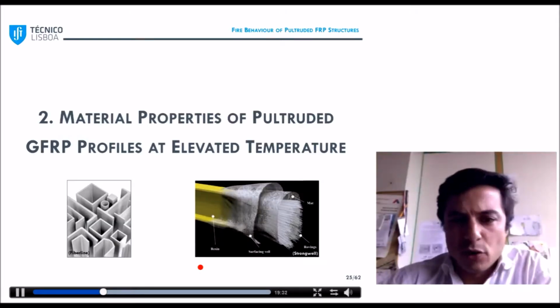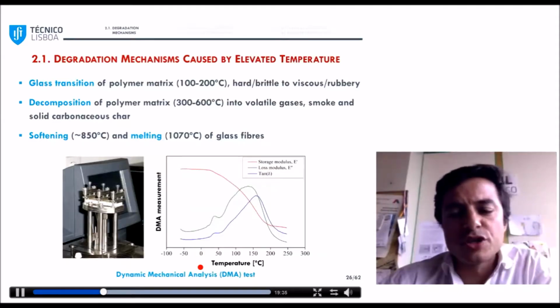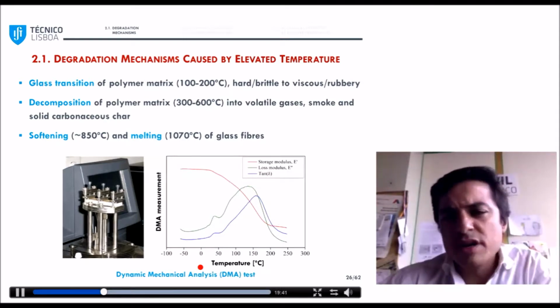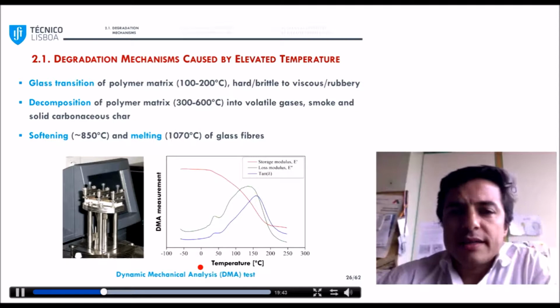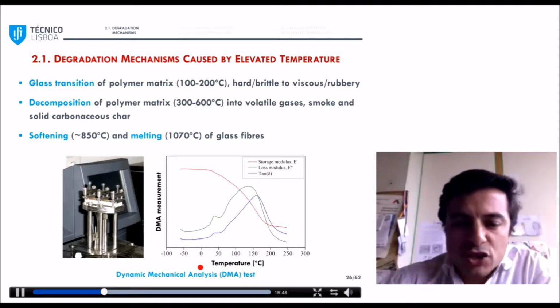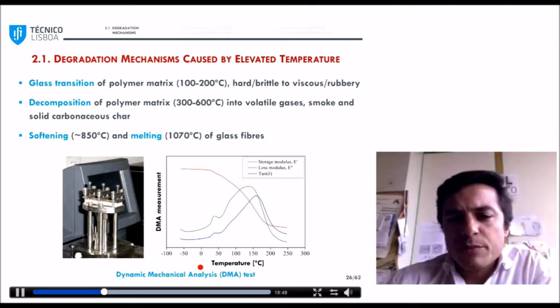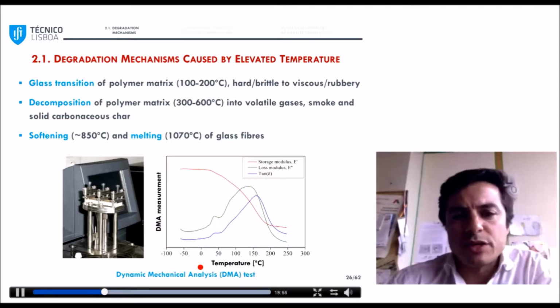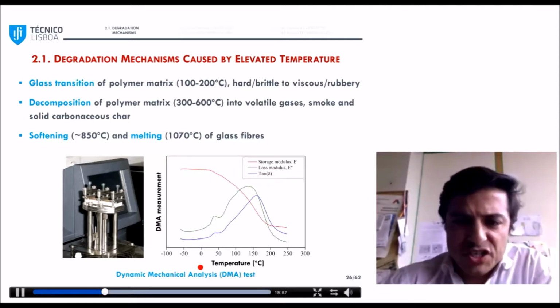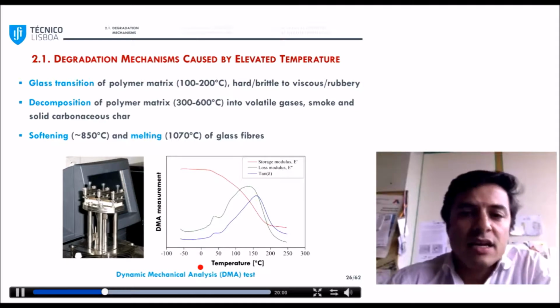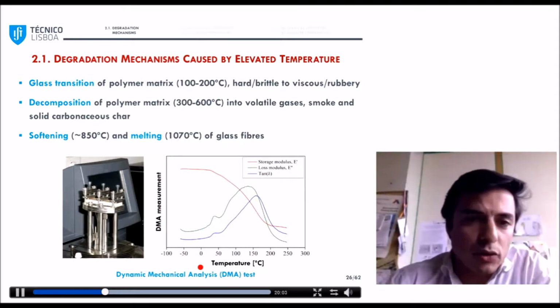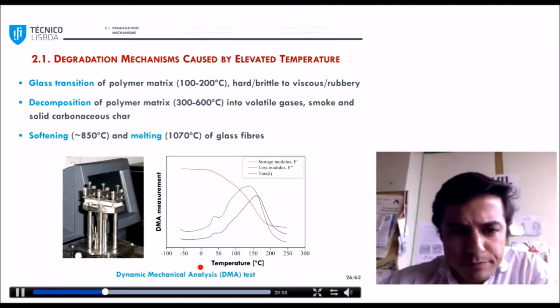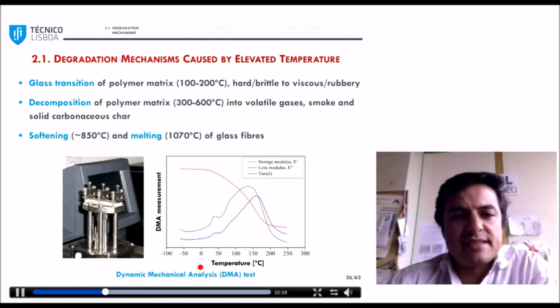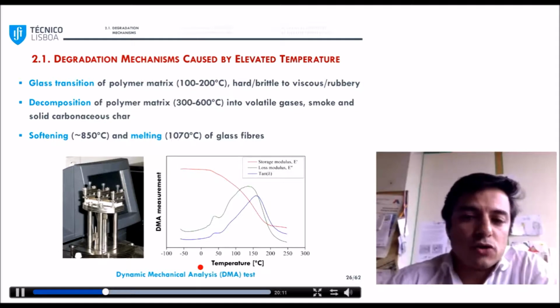So starting with the GFRP material properties at elevated temperature, we need to go to the degradation mechanisms at elevated temperature. And as you may know, high temperature affects especially the polymer matrix. So for temperatures between 100 to 200 degrees, depending on the type of matrix we use, the material changes from a glassy state to a viscous or rubbery state in a process called glass transition. This process can be assessed in different ways.